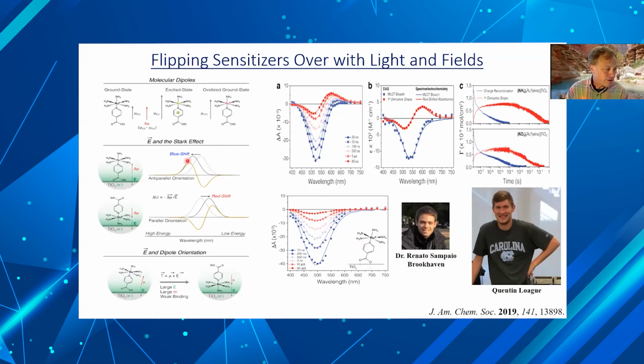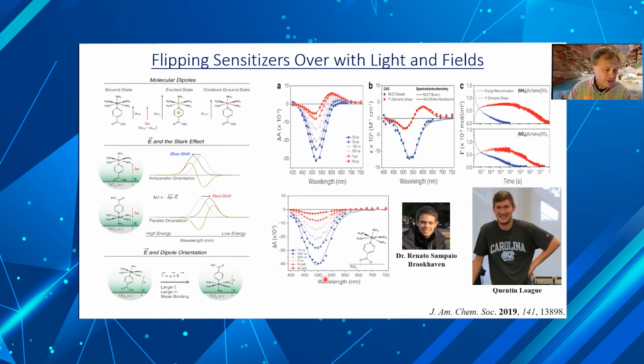Without going through all the details, if the field is parallel or anti-parallel to the orientation of the dipole of the dye, we get a blue shift or a red shift. So it's kind of a sore thumb in our experiments. When he bound this ruthenium pentaammine dye through carboxylic acids, he could see right in the ground state spectrum a shift that reported on the electric field. When he made the ester version of the dye, what he found was that the magnitude of the field and the Stark signature, as we often call it, changed sign.